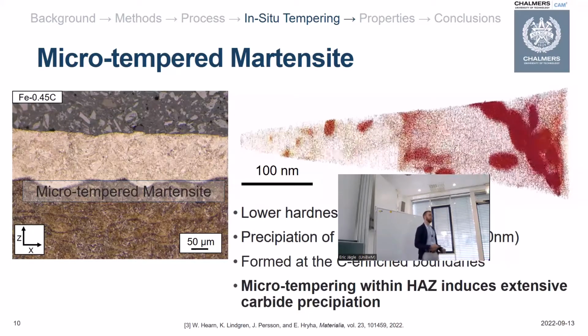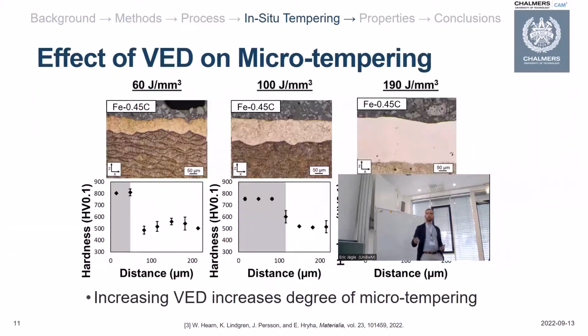And how this relates to increasing your energy input is that we found that the level of micro-tempering within your heat-affected zone would increase as you increase your volumetric energy density, as the hardness in the regions just below for the specimens would decrease by up to 20 to 25% as you increase your energy input. And the reason for this is, I think, also somewhat straightforward. You just look at the size of your top layer or the melt pool you're forming. I think other works have covered this much better, especially with operando work. But as you would expect, as your melt pool gets larger, the rate of heat dissipation slows down. You're inducing a longer solidification time, which allows for greater tempering of your material to occur.